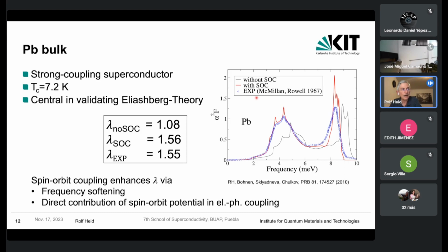data. Now, without spin-orbit coupling, which is then here this black line here, one sees clearly deviations to the experimental spectra. And also the coupling constant is significantly smaller than in the case we include the spin-orbit interaction, which then gets close to the values which have been extracted from experiment. And that shows that for lead, which is a heavy metal, this inclusion of spin-orbit interaction is really very important to describe the pairing and the electron-phonon interaction in this material on the quantitative level.